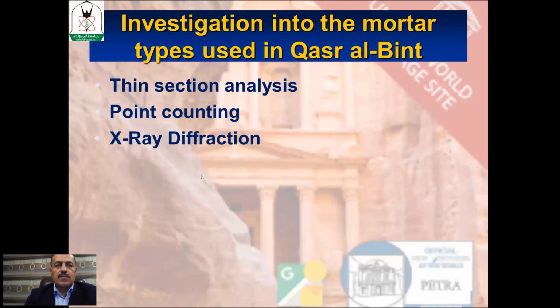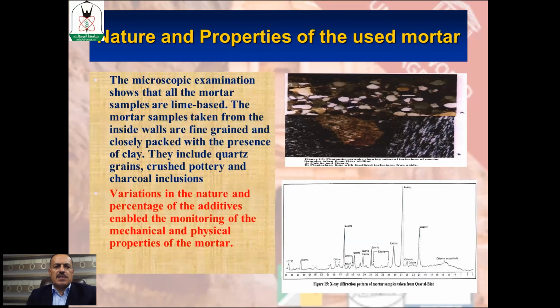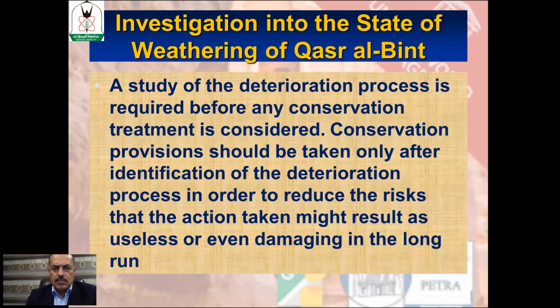We also identified the mortar type used in Qasr al-Bint using thin section analysis, point counting, X-ray diffraction, and microscopic examination, so that all the mortar samples are lime-based. But it's very important that we identify the exact formulation of the mortars and additives and some physical and chemical properties of the mortar, especially if conservation using mortars is considered, in order to use this formulation in future conservation.